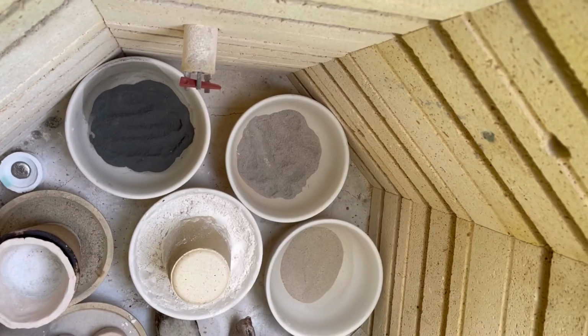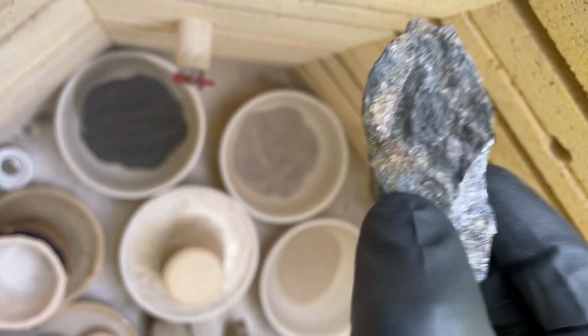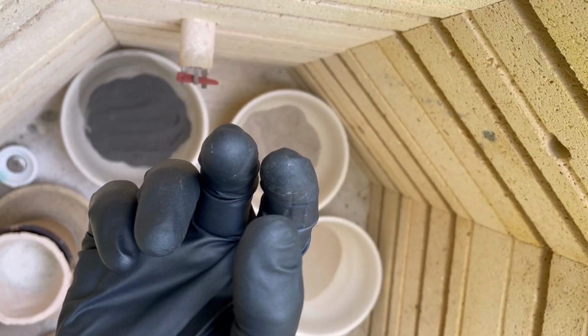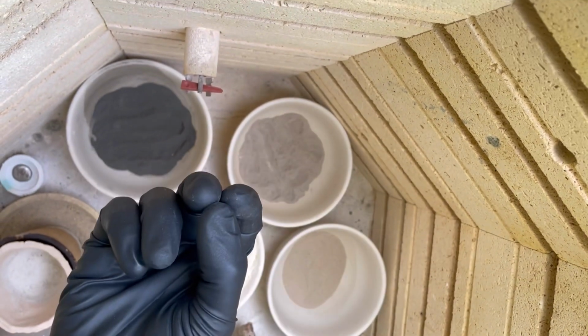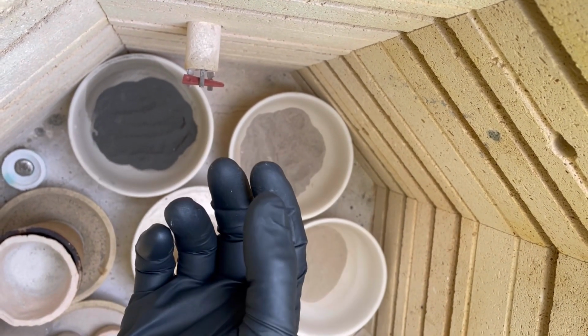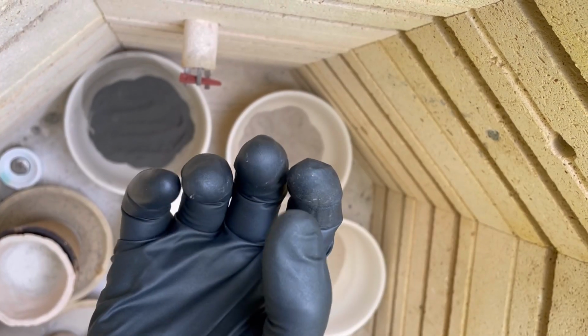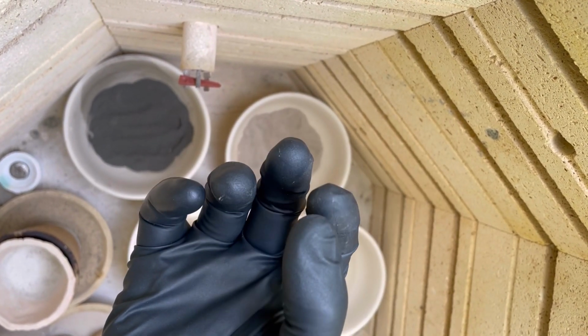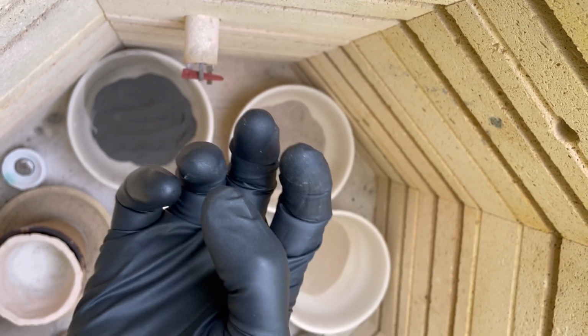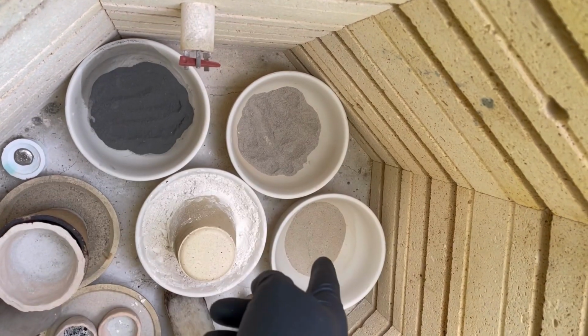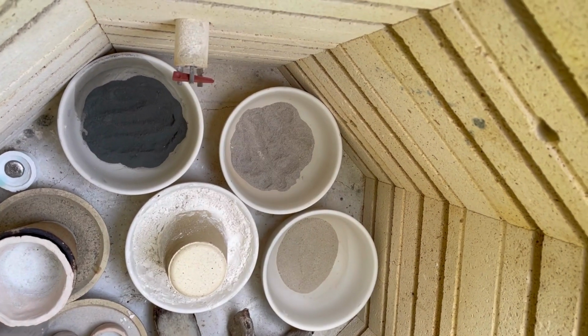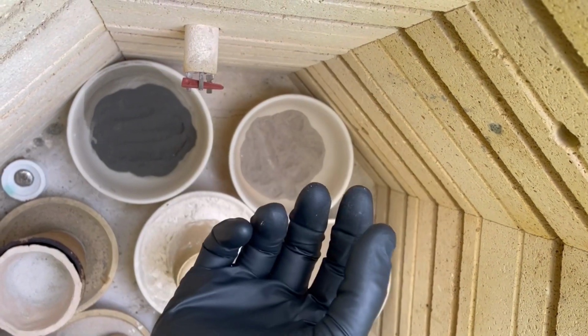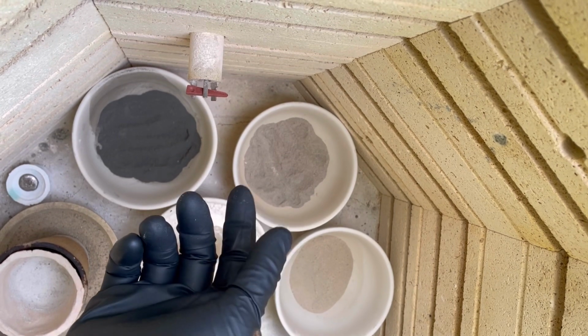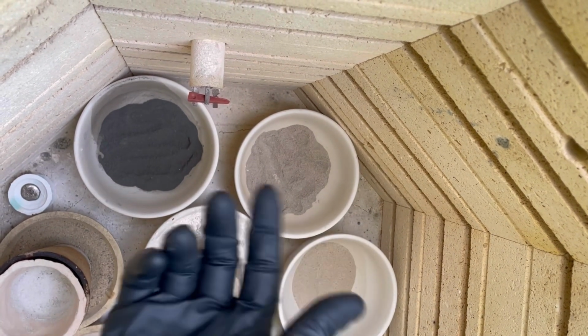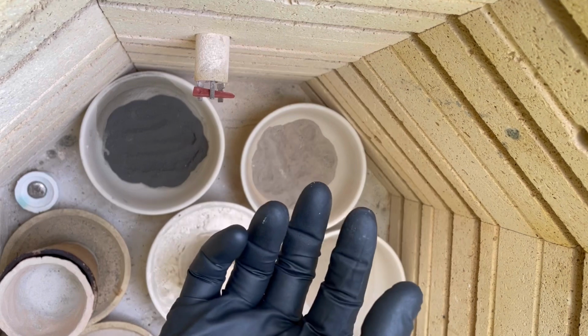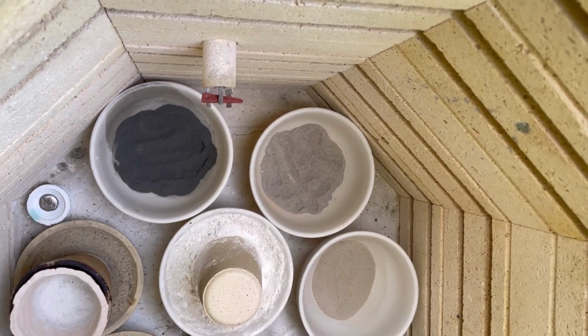And if the lead particles are too close together, then they'll coalesce and then sink down to the bottom, where it's very difficult to further oxidize. So you want to spread it out so the oxygen can get to all the lead particles. So you'd want to mix it with something fluffy like silica sand. Also, you don't want to get it hotter than the melting point of the oxide. That's not a problem for the iron, but for lead, that would make things stick together and be very difficult to remove from the bowl.